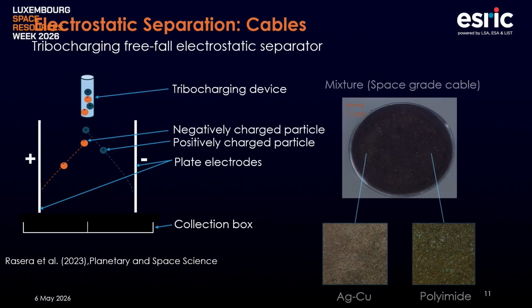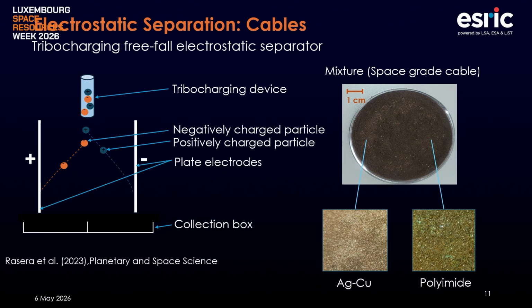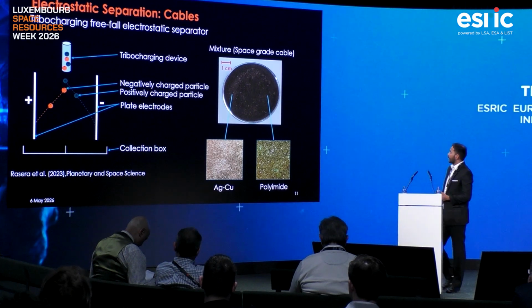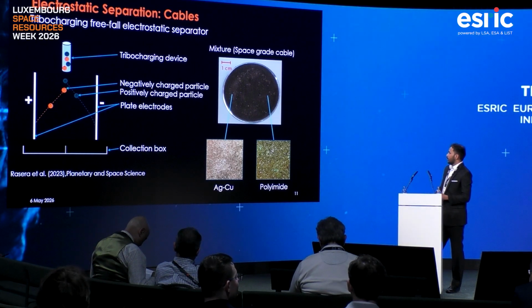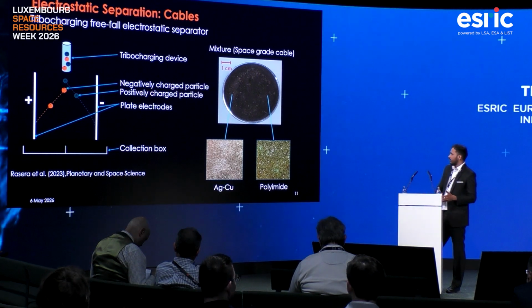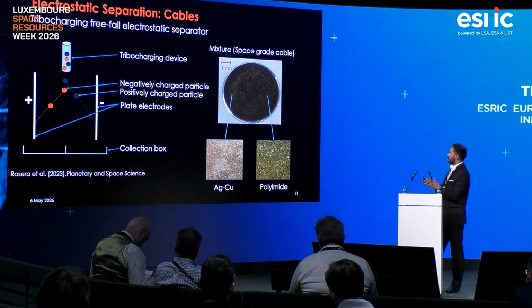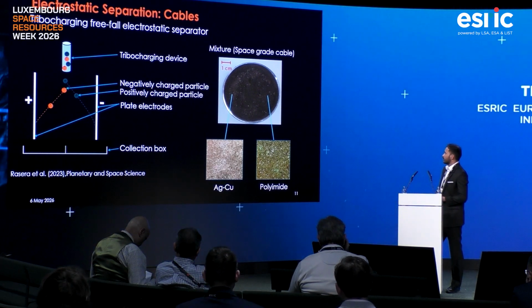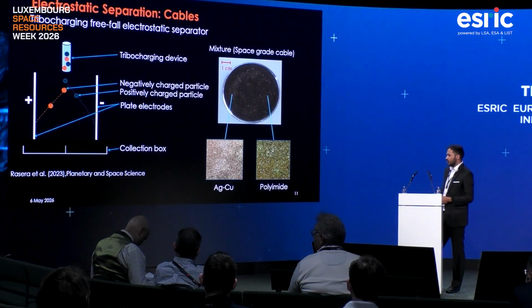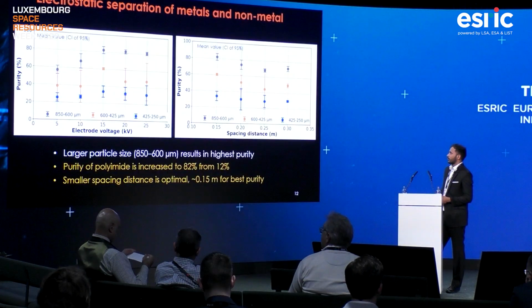Here you can see the mixture from the space-grade cables, and you can clearly see a good separation between the silver-plated copper and the polyimide, because this space-grade cable is made of silver-plated copper as a conductor and polyimide as an insulator. You can see that a clear, good separation was achieved using this triboelectric free-fall electrostatic separator.